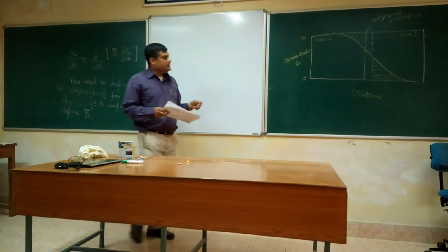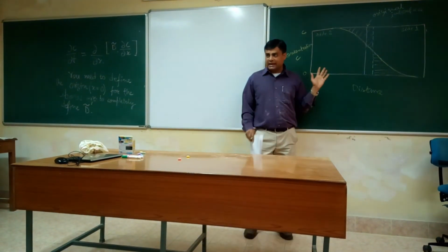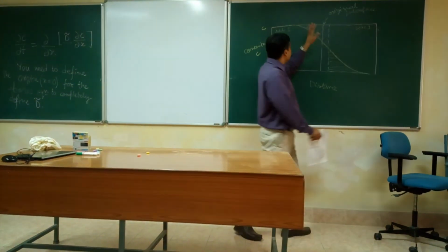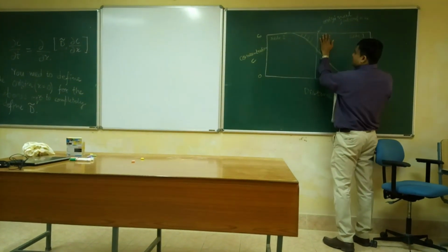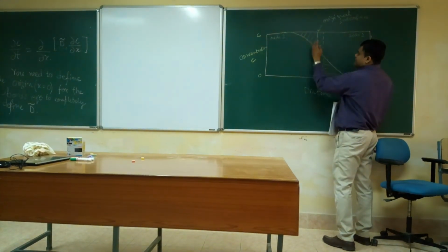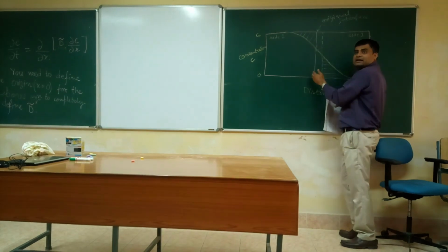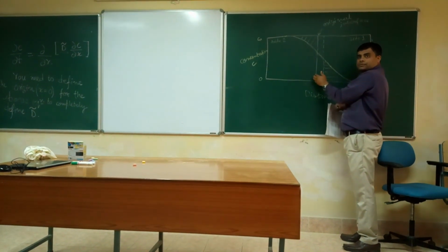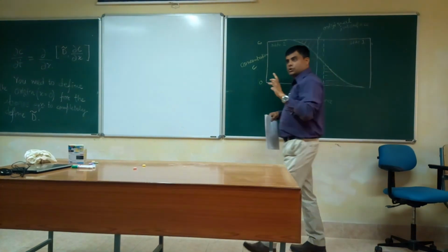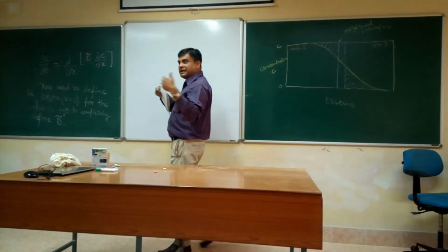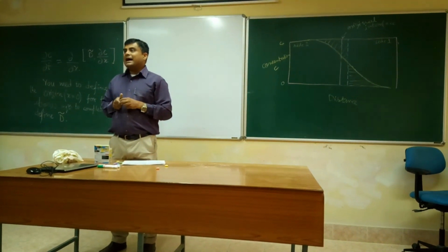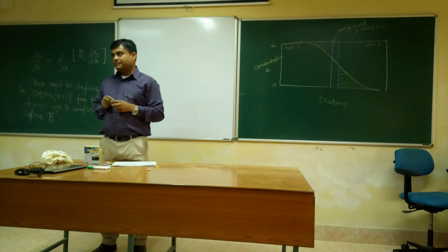Now after annealing for a certain time, usually what you will find is that the composition profile, this yellow line, is not symmetrical about the original interface. This happens because of the interpenetration of the individual component elements, which are diffusing at different rates.